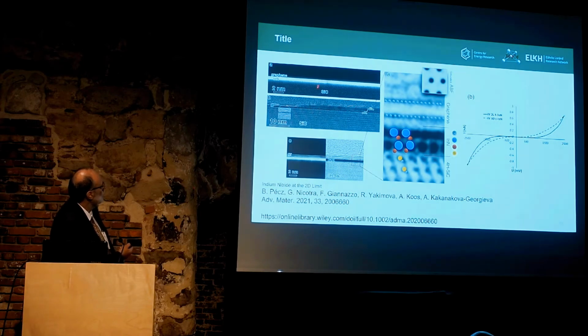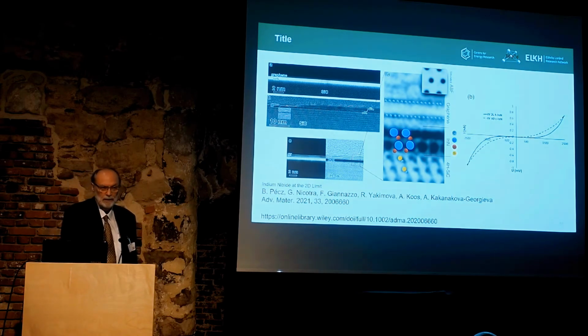And then we studied this bilayer structure, we determined the structure, and also could measure I-V characteristics. And from the I-V characteristics, we learned the most important property of this semiconductor, the band gap, is 2 electron volts, instead of the 0.7, which is characteristic for the bulk material. So the basic properties of the two-dimensional semiconductor are completely different from the bulk ones, and microscopy contributes to this research, I believe. And with these words, I call my colleague Peter to speak on these results. Thank you very much.